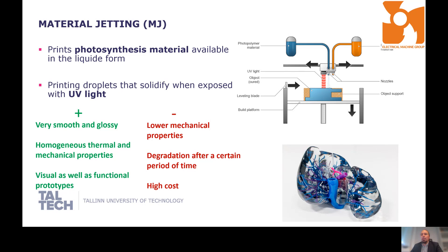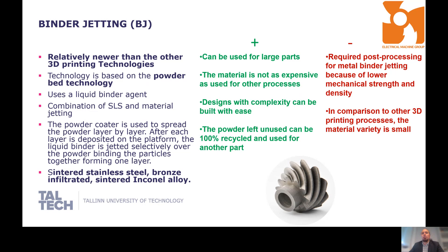Binder jetting is already allowing us to print metal parts. The printer works with metal powder and a binder agent that glues together all the metal parts. It is a very interesting printer. The only problem is that the material characteristics you get out of it are not suitable for printing electrical machines because the binder does not give very good mechanical strength or electromagnetic properties. It is good for producing nice objects, but for real tooling and building electrical machines, it is not a very suitable printer.